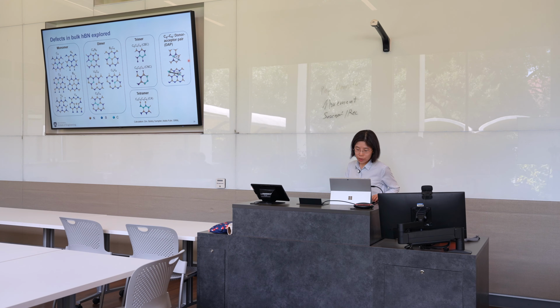at a number of defects in boron nitride. These include monomers, for example, single carbon substitution, antisites, and vacancies, as well as dimers, which are combinations of these monomers, as well as trimers. In particular, we're looking at the so-called CBC and CNC. CBC is carbon substituting boron, nitrogen, boron sequentially, and CNC is carbon substituting nitrogen, boron, nitrogen sequentially. We also looked at tetramers as well as the donor-acceptor pair, or DAP. This DAP is carbon substituting boron and nitrogen, but they're not adjacent to each other.